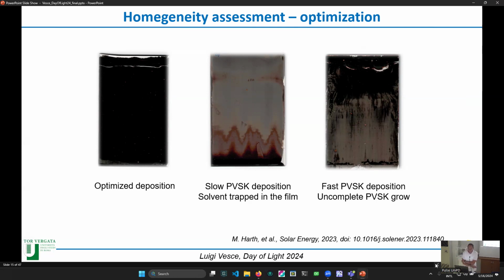In the middle, you can see what happens if the deposition of the perovskite, for example, is too slow. Here we notice that the solvent is trapped in the film, so you do not have the conversion of the perovskite. And on your right, you can see what happens if the perovskite deposition is too fast, so you cannot have a complete perovskite growth.